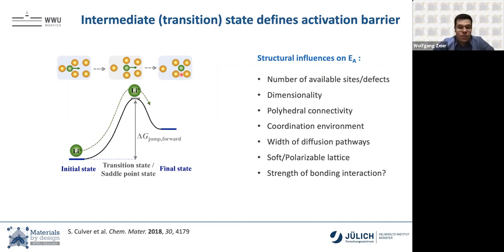And now, depending on the structure and how the coordination of the ions are, we get a certain energy landscape. So for instance, if we assume that this ion is just much more happy being trifold coordinated, it'll have a lower energy than here in our square planar coordination. Meaning that even if we overcome the barrier, the lithium would sit here and it has a much higher probability to just jump backwards. This is the baseline of the structural community, that we know that our crystal structure itself gives us the energy landscape of the ion, or at least that's what we mostly think of.